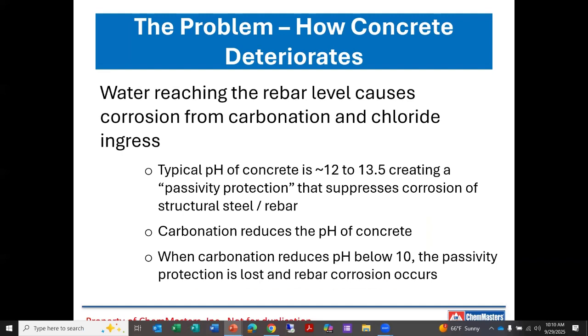Rebar and other structural steel has a passivity protection within concrete. The high pH of concrete, which tends to be about 12 to 13.5 as it's placed, suppresses corrosion. And so for some period of time, concrete has a fair amount of protection just by virtue of that high pH. Unfortunately, carbonation reduces the pH of concrete, and that can occur over time, and it can occur rather quickly in certain circumstances. When the carbonation reduces the pH below 10, that passivity protection is lost, and rebar can now corrode readily.